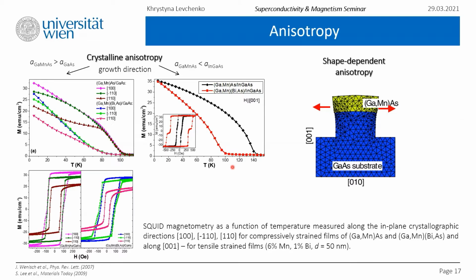And this is only the original crystalline anisotropy, which we can manipulate by introducing different buffers, also different dopants, like, for example, bismuth. We also can introduce artificial shape-dependent anisotropy by patterning our layer in such a way that the top layer is so thin that the strain-induced relaxation processes force the spins of the magnetic ions in our top layer to be aligned along, for example, a very thin stripe patterned by lithography. This we will see further.